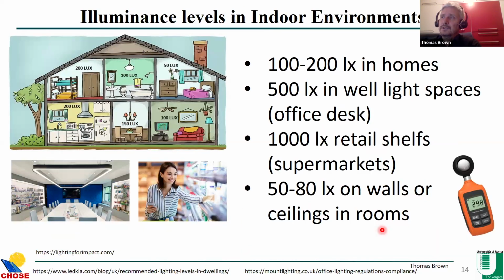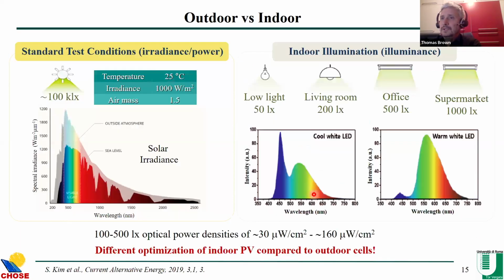What about the illuminance levels in indoor environments? So in homes, the illuminance levels are around 100 to 200 lux. Whereas in offices, where you need to read, write, and so on, the illuminance levels are higher, around 500 lux. In retail spaces, you can find 1,000 lux. Whereas on walls or ceilings in rooms where there's not really direct light, the lux levels are around 50 to 80. So there's a broad range of lux levels which need to be considered when both developing photovoltaics and also implementing and applying them indoors.